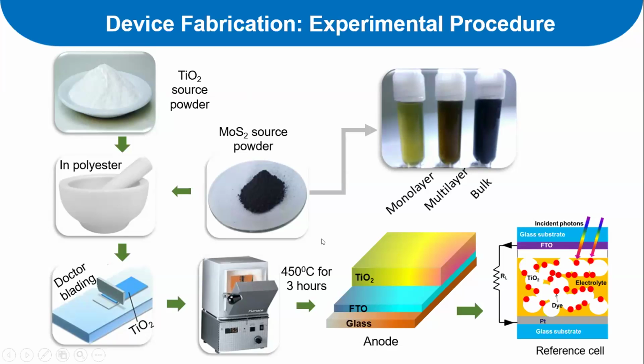Once we have that, we have the structure: a glass substrate on which the transparent conductor, either fluorine-doped tin oxide or indium tin oxide, is coated. On top of that, we have titanium dioxide as an electron acceptor. So now we have this as an anode. We don't call this a photoanode because we don't have the photo-absorbing material candidate in it. We have only the electron acceptor structure, so we call that an anode. Once we have that anode, we need to put the organic dye molecule or quantum dot on top of it. Then this becomes a photoanode. That means it is ready for photo absorption.